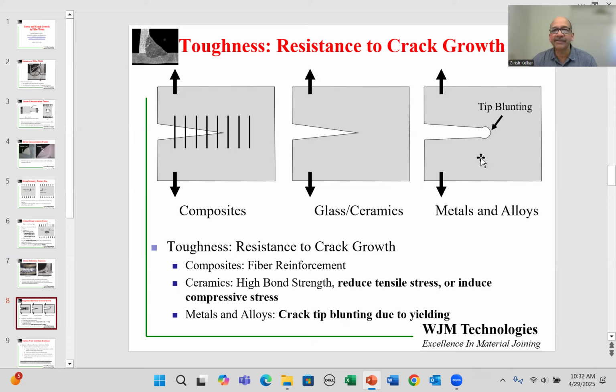So in metals, the best way we can handle that is to provide crack tip blunting. That means have the material soft enough that when we have very high stress at the crack tip, it actually blunts, in the sense that we have a lot of localized yielding. And now the tip, being sharp, has become a blunt tip, and then it is more difficult for it to grow. So we have two different strategies to reduce crack growth. One is to reduce the overall stress, or actually to apply compressive stress, which will actually close the cracks. Or we can change the material characteristics by reducing the hardness of that component.